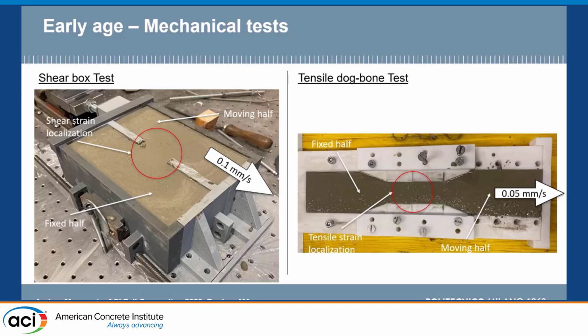So 0.1 millimeter per second for the shear test and 0.05 millimeter per second for the tensile test. Then an LVDT is measuring the displacement during the test, and a load cell is recording the load required for the movement, so that the output curve will be load versus displacement, and it is processed in order to obtain the stresses from the load. So the final output of the tests will be the stress-displacement curve.